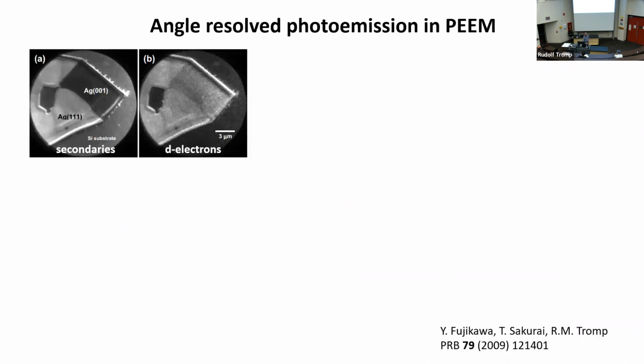Now, photoemission is a rather complicated phenomenon. Here's an older experiment where I grew a silver flake on a silicon crystal. This part of the flake is silver 111, and this part is silver 100, just by accident. This is what I found in the sample. This is imaged with secondary electrons. This is imaged with d electrons. So these are photoemission images where I selected different electron energies on the sample.